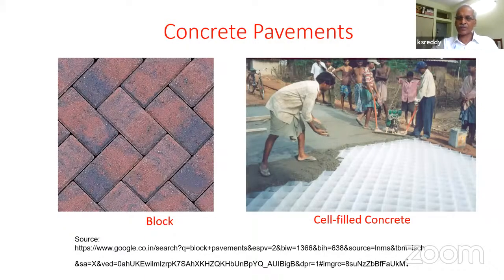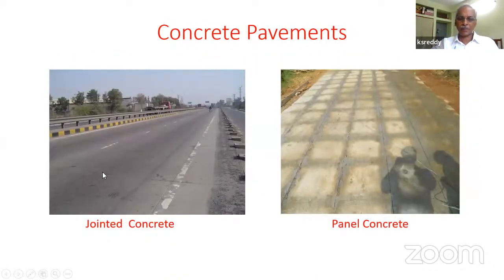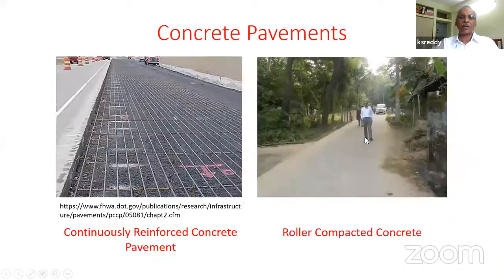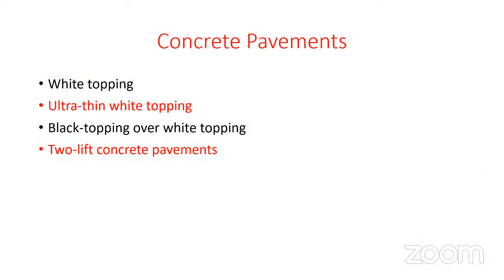So you have different types of concrete pavements, starting from block pavements, precast, cast in situ block pavements, and typical conventional highway concrete pavement, smaller panels, and continuous concrete. You also have what is called white topping, concrete over asphalt layer, bituminous layer, and among white topping, the concrete layer being thin, thick, different kinds of names that we use depending on the thickness of the concrete layer. And you can also have black topping over white topping, bituminous layer over concrete layer. We also have the total thickness of concrete placed in 2 layers, wet on wet, and then maybe you can use inferior grade of concrete at the bottom layer, and the upper layer could be the functionally required layer with better quality aggregates.